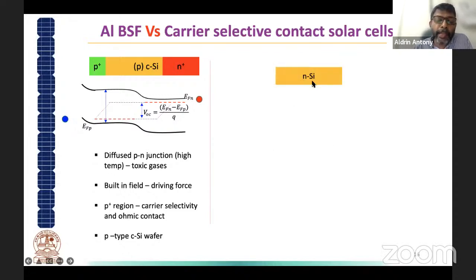That is, you take an N-type silicon. So then itself, there will be a lot of marginal difference. If you're having a P-type crystalline silicon, it is having a lot of defect states compared to N-type silicon. So N-type silicon is having fewer bulk defects compared to the P-type silicon because of some boron-oxygen complex formation in the P-type silicon. So normally the bulk lifetime of the minority carriers in N-type crystalline silicon is high. So that's why N-type crystalline silicon solar cells can achieve higher efficiencies.